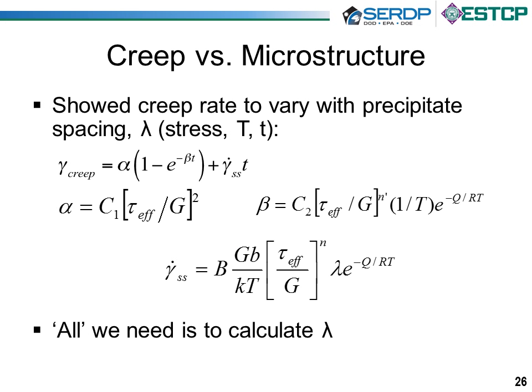So as one deliverable out of this, we looked at how we could express the deformation properties, the creep rates. Remember, we need the creep rates to model, and so we looked at how we can express the creep rates as a function of these precipitate distributions. And we showed that they can be expressed simply in terms of the average spacing between the precipitates, as well as a whole bunch of parameters that we went and measured, you know, the constants and the temperature dependencies and so on, of properties, but including a factor in there denoted as lambda, and this lambda factor is a function of the precipitate spacing, which changes. So aside from these constants that we're giving you, and that's a pretty standard approach, we need to calculate the precipitate spacing.